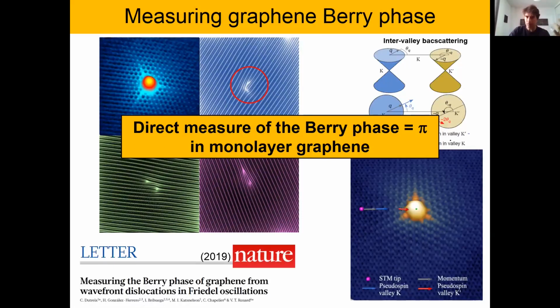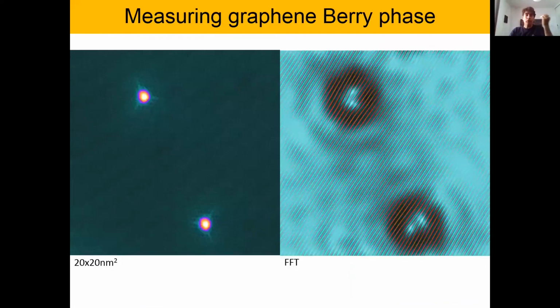Okay? So the message here is that we can obtain the Berry phase using STM without applying the magnetic field. And the only thing you need is a very clean surface. You need not to have any other adsorbates, because if not, the Fourier transform gets messy. But then you have two adsorbates here, for example, far away, and then you can measure here the two dislocations in one direction, and here the two dislocations in the opposite directions, because they are on opposite sublattices.